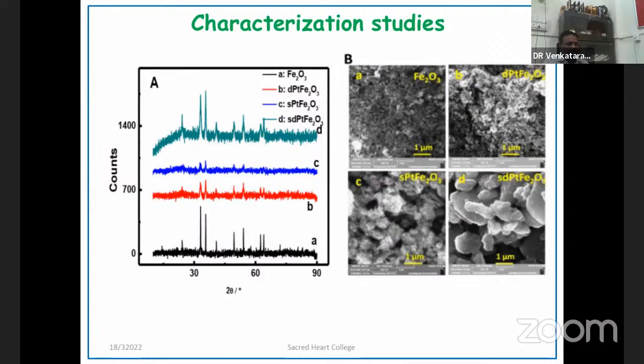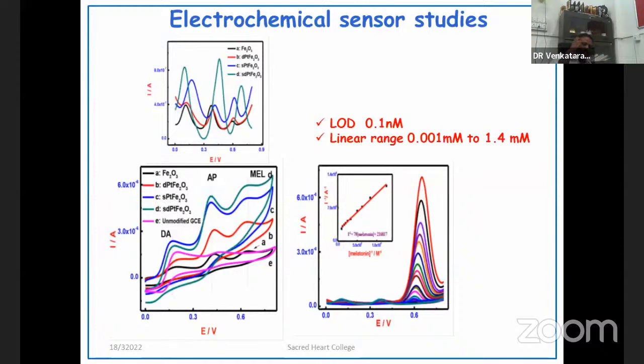With reference to that, we can conclude that the composite was formed from the iron oxide and the platinum. Here are the morphological features, and once you get the linear range and other things, you can correlate that some morphological features can influence the detection limit or the linear range. Simultaneous sensing of all three analytes is different, because once you develop a new material, you have to distinguish each component's contribution. That is why you have to make measurements for each component which constitutes the composite.